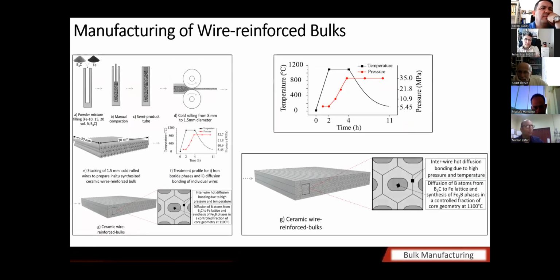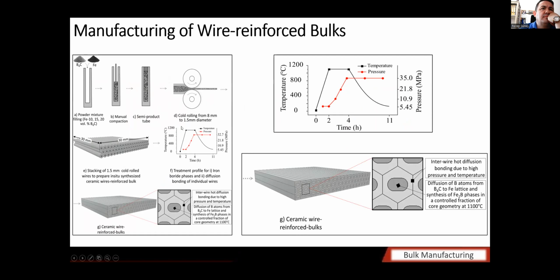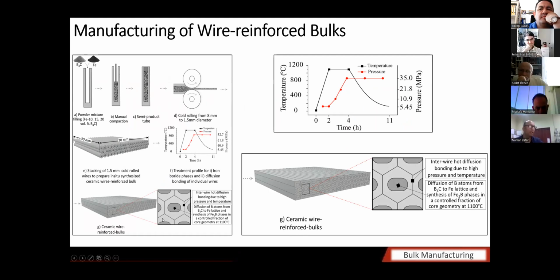These are the schematics of bulk manufacturing. Already explained until this. 1.5 millimeter cold rolled wires are stacked together, and then they are subjected to this heat treatment. And eventually we expect something like this. Diffusion of boron atoms from the B4C particles to iron, and synthesis of iron boride phases in the cores, and interwire hot diffusion bonding at the sheaths. So again, this treatment is the same as the old one.